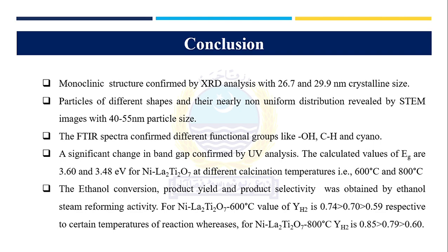At the last, there is a conclusion, which explained that the monoclinic structure was confirmed by the XRD analysis with 26.7 and 29.9 nanometer crystalline size. The particle size was confirmed by the STEM, which is 40 to 55 nanometers. The FTIR spectra also confirmed the different functional groups like OH, CH, and cyano. The significant change in the band gap was confirmed by UV analysis. The calculated values of the band gap, as I explained, are 3.60 and 3.48 electron volt.